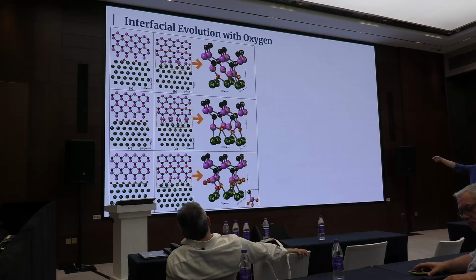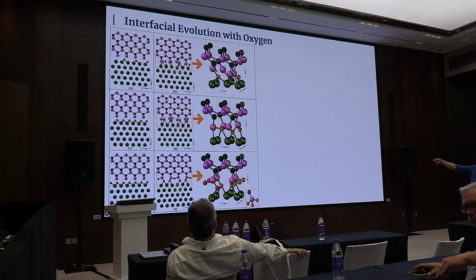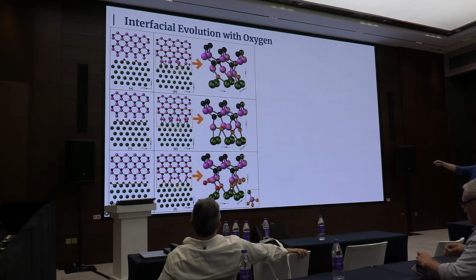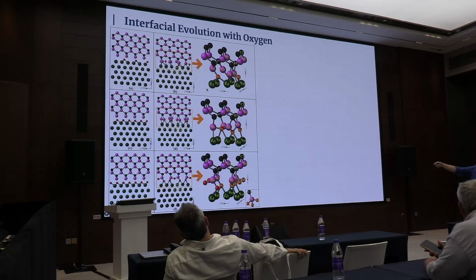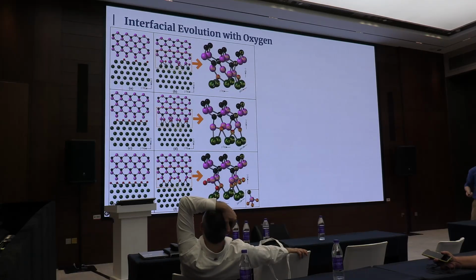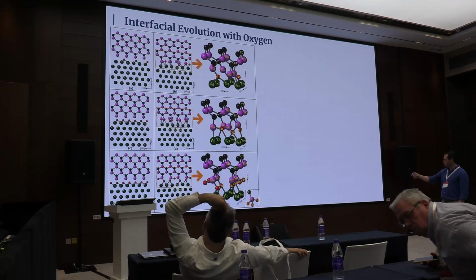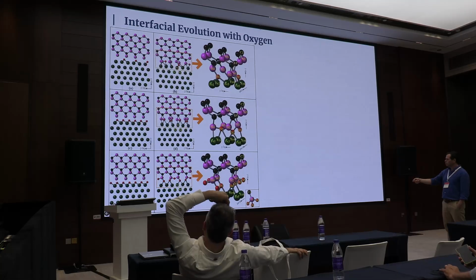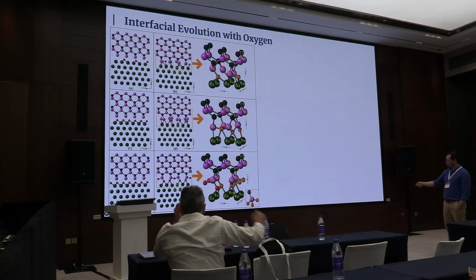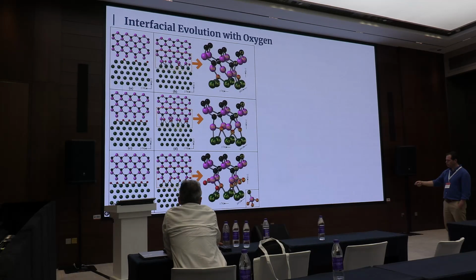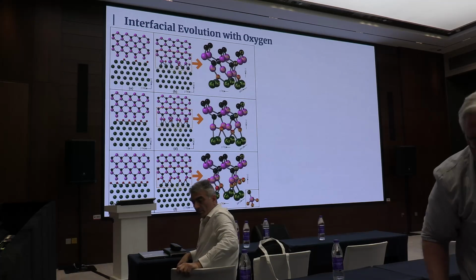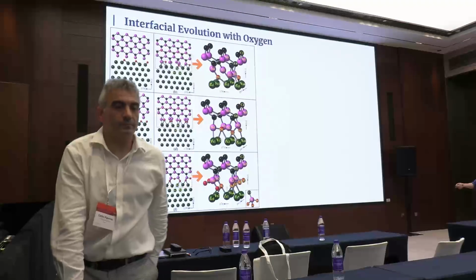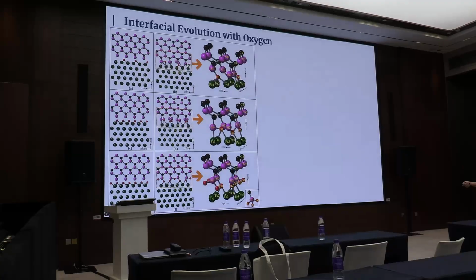You can see here where the oxygen is located, the immediate silicon is not bonded directly to the iron. It's the oxygen that is taking this place, and we have a silicon-oxygen-iron bond. And as soon as more oxygen appears, this effect shows more. Even in this part, when the full monolayer is complete, there are no more iron-silicon connections. There's no more direct bond between these atoms. So the bond at the end is just directly through the oxygen. The oxygen is the intermediary of the connection between both surfaces.